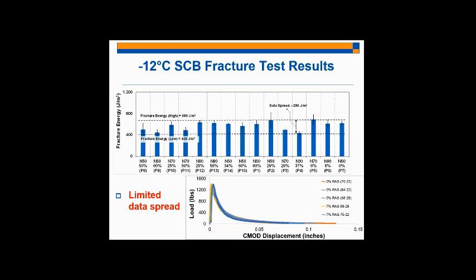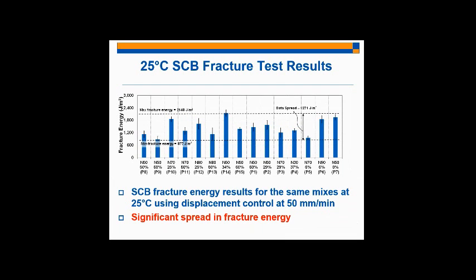And so this is the issue with the low temperature testing condition, that we don't have significant spread in our data. And we need significant spread if you remember the test selection criteria. Because I know that these mixtures are performing differently in the field, and their mix design properties are very, very different. So with this issue identified, we shifted to basically 25 degrees Celsius.